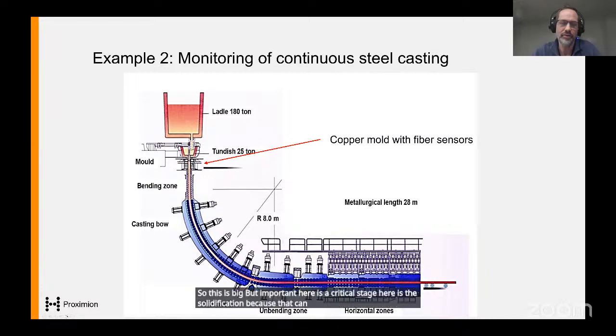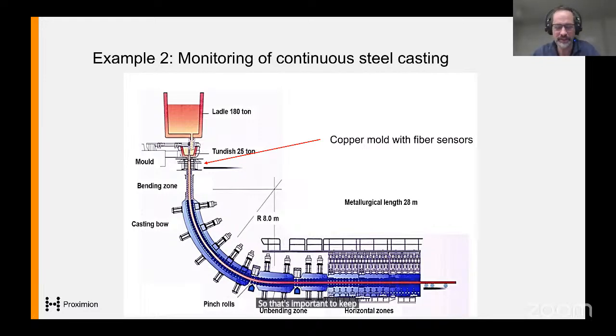quality, and if you're unlucky, you can also get a stuck surface of the steel, and then you can get a breakout where you have steel flowing all over here, and that ends up quite expensive, because it's a bit tricky to remove solidified steel over all these rollers and equipment. So it's important to keep track of the temperature in these copper plates.